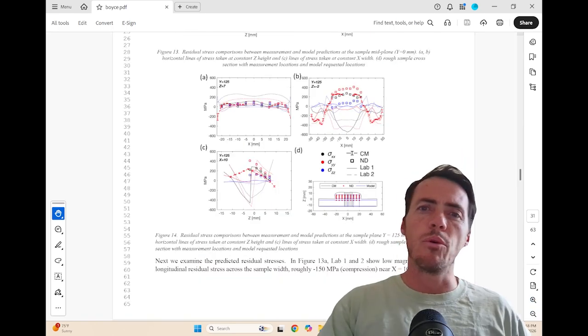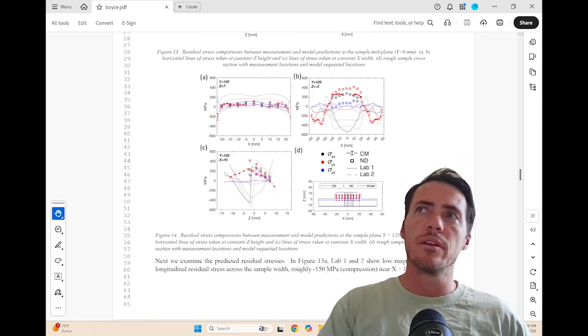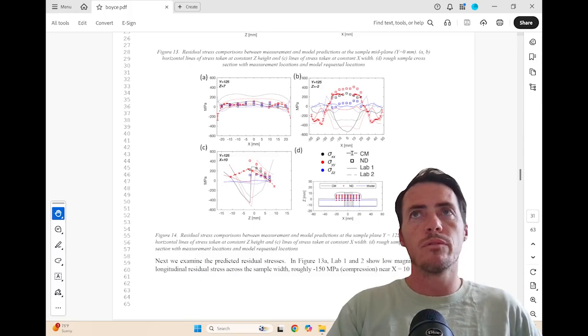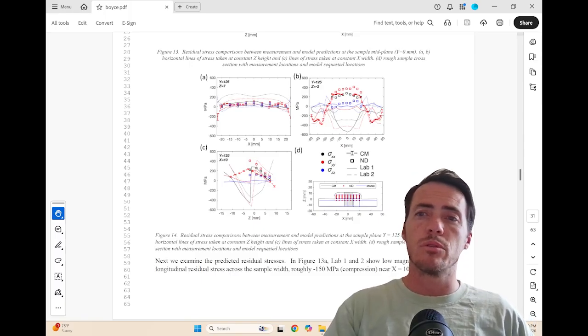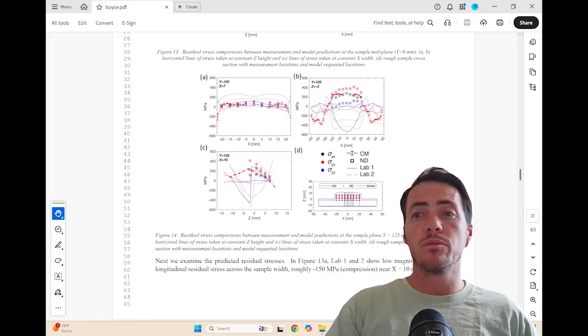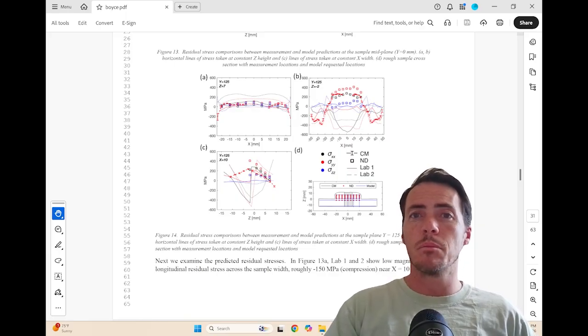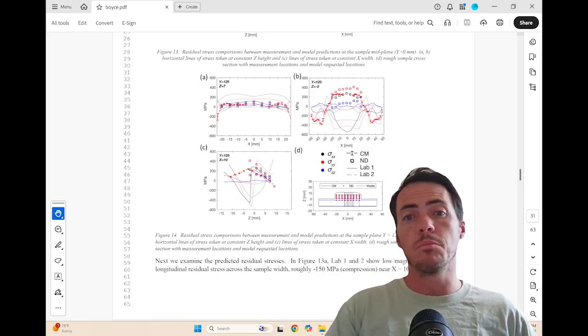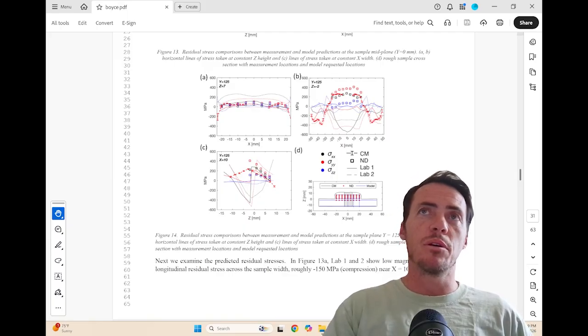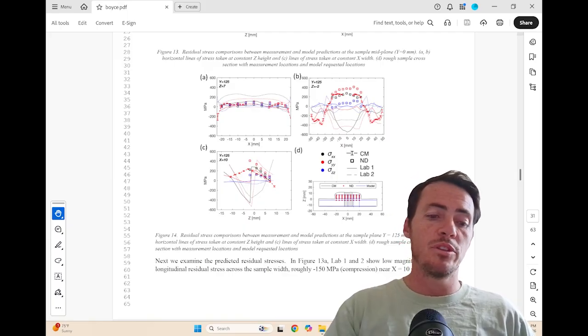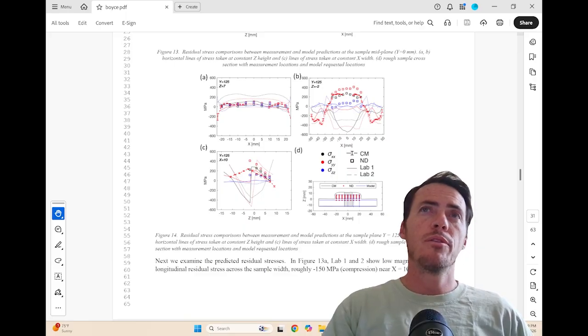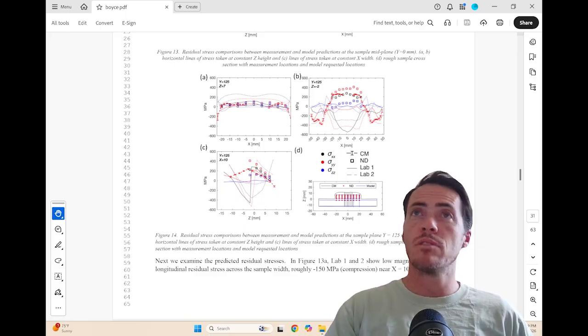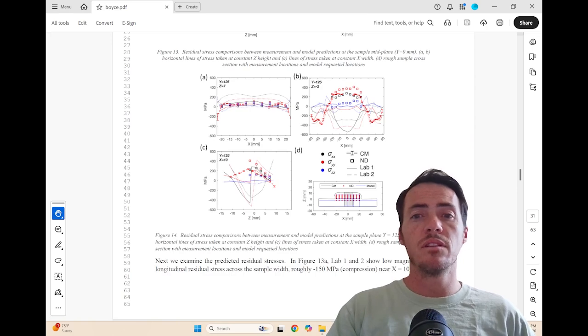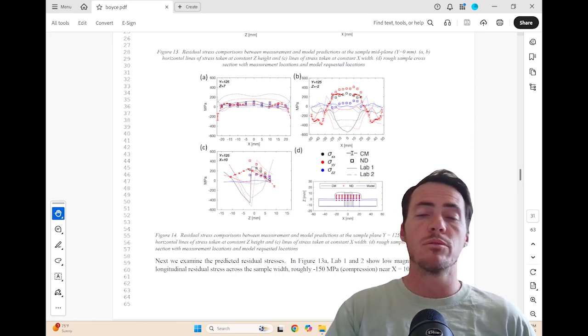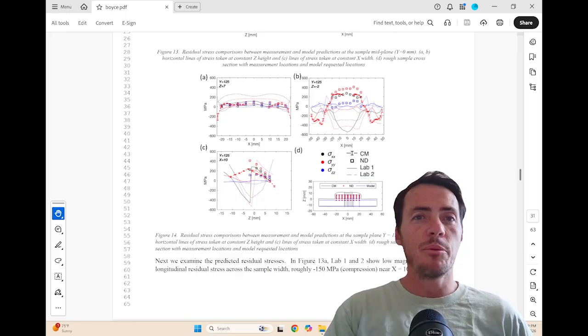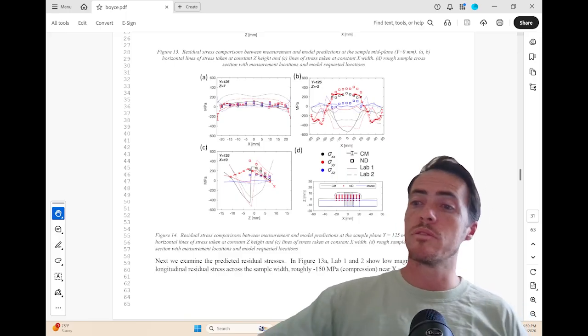And maybe that's the big takeaway from this study is that in the past we've relied on things like temperature and warpage, which provide sort of useful validation metrics, but they clearly don't tell the whole story because at least one important metric is this residual stress, and it seems to be the true discriminator between better and worse models, right? And if you're getting your model right in temperature and warpage, you might still be getting it wrong in terms of stress. The authors point out some of the reasons why that might be. Phase transformations, transformation-induced plasticity, constitutive behavior, or even incorrect boundary condition assumptions. But the point is, now they've actually created a resource that the community can use.